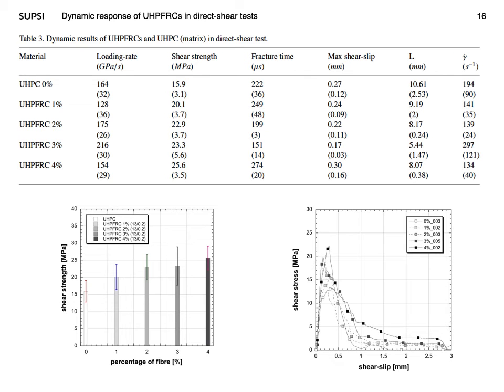The fiber orientation and distribution have a strong influence on the tensile and also in the direct shear behavior. Increasing the fiber content, increased peak stress and post-peak stress is obtained. When the orientation of the fiber is well distributed along the loading direction, the behavior tends to pseudo-elastoplastic or strain hardening behavior. The influence of the fiber percentage